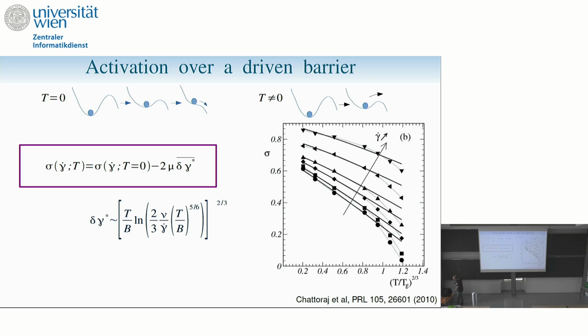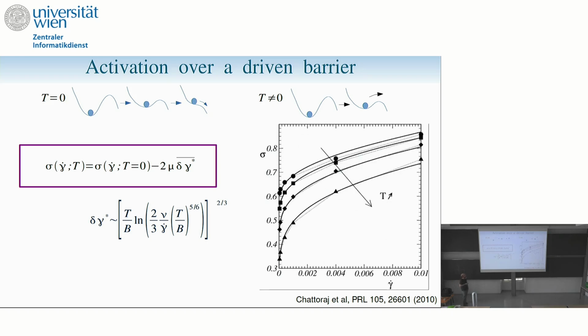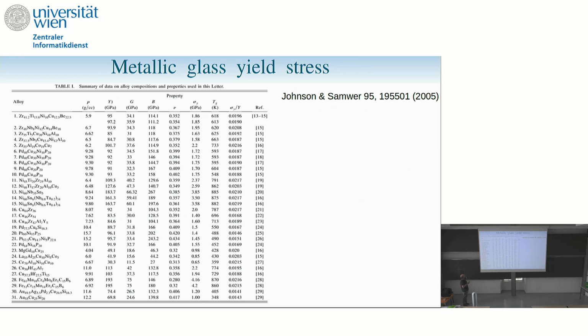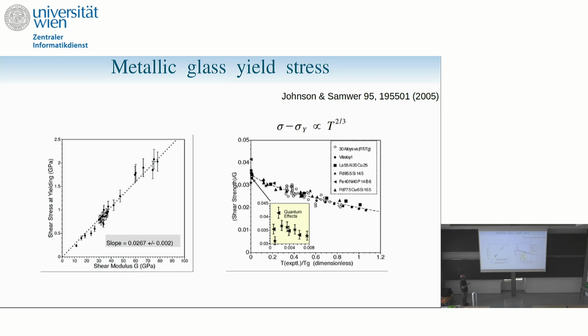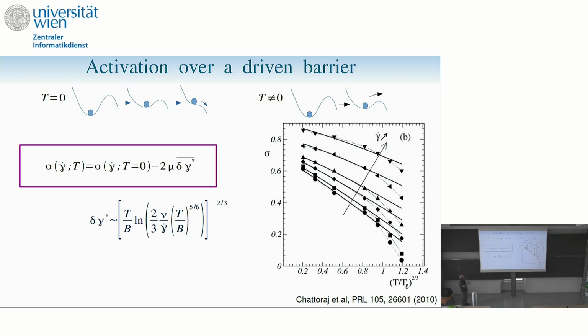I wanted to insist on this because you might encounter systems where you think thermal effects don't play a role. Temperature is very small. Even when temperature is very small, you have a singularity of the effect of thermal activation on stress, which is something to know. It was actually shown also in metallic glass by Johnson and Samwer. They took lots of metallic glasses, and they saw empirically a difference in the yield stress with this T to the 2/3 law, which comes out exactly from this argument up to some factors.